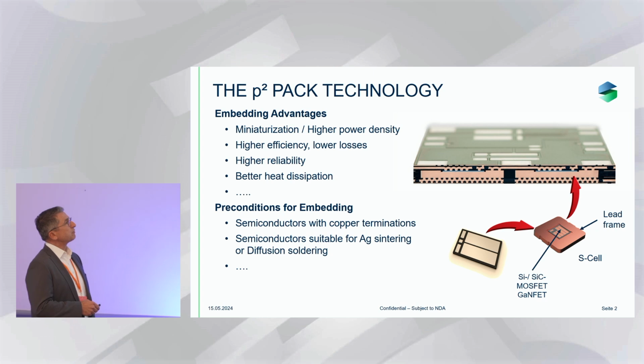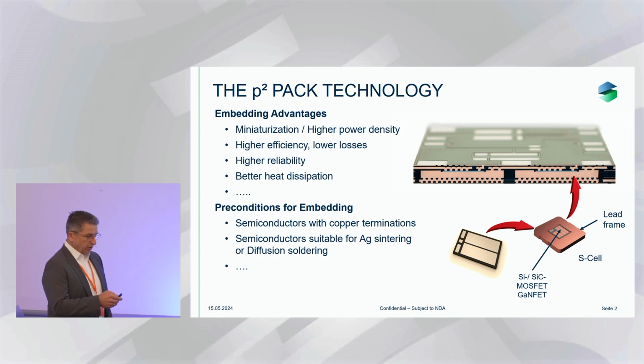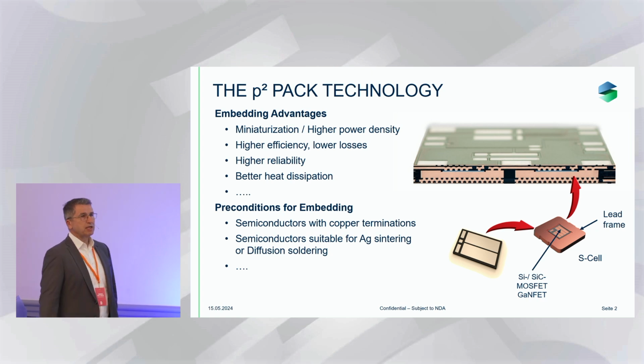I want to highlight, first of all, the technology that we use for embedding. As mentioned earlier in the panel discussion, we are not using bare die embedding, but we're using an embedded component consisting of a lead frame with a cavity on the top side, and inside the cavity we have the power semiconductor. This brings all three contacts to one common level. That means the drain contact is represented by the lead frame, and therefore, here at the top you see a cross-section through such an embedded device, and the drain contact can be taken from the lead frame side.